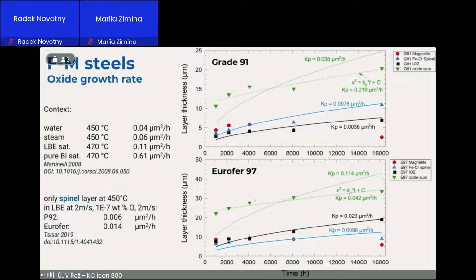Here is a fit of each sublayer, with the same kinetics like before. And you can see that only the grade 91 spinel layer follows this parabolic curve. So it means that this corrosion process is controlled by diffusion. I would not say that I can fit this model to the total oxide thickness. You can see here it doesn't follow it, unless I introduce the integration constant, then it's highly questionable how to explain this model. And it's on par with what we can get at the same temperature in water, like this constant, basically.